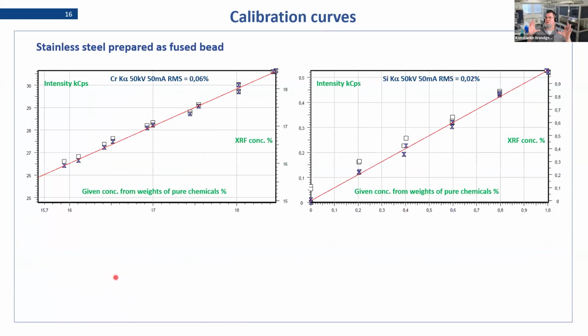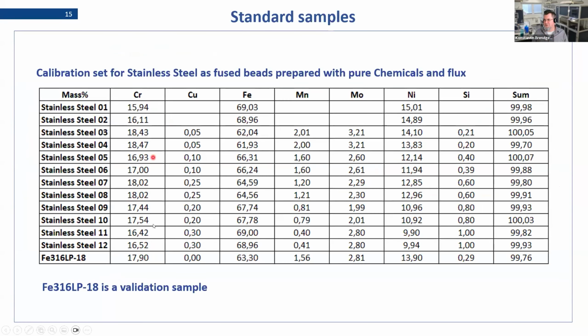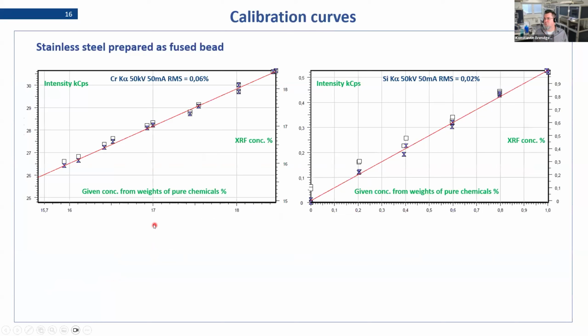So we used this one as a validation sample in order to check how our synthetic calibration holds up. And since we are within a very strict matrix, where this is all the same, if you look at the ranges of our standards here, this is a very narrow range. So what we ended up with was a nice correlation and no need for matrix correction. In this very specific application or method, it is very simple to make a calibration, and you get a very nice fitting, as you can see, very low RMSs across the board, even without any form of matrix correction. So we were just doing base curves here.